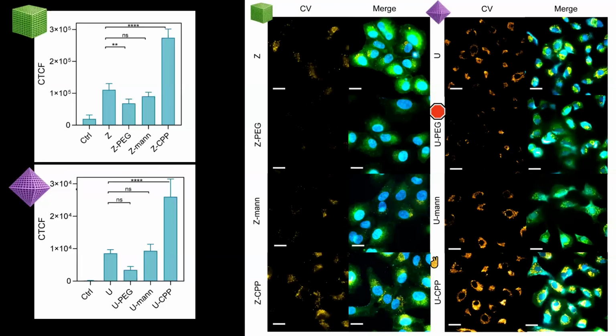Okay, so we have the MOF, and this MOF has a complex chemistry on top of it, and normally they are positively charged. And then when you put the PEG, internalization goes down. And then we put mannose, a carbohydrate, expecting that it will bring a lot of particles inside because these cells express a mannose receptor, but it didn't work. Okay, I don't know why. It's something we have to work on, because maybe the mannose is a little bit inside the MOF, or it's not outside, or we don't have enough density, or whatever. It doesn't work. That was what we wanted. But the cell-penetrating peptide, it works very well. So you have tons of particles inside. Okay. It's not about charge, it's about interacting with specific receptors and so on.